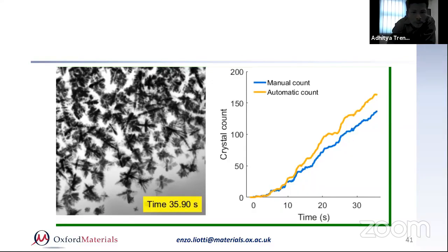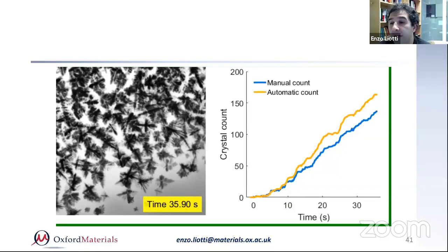Maybe the type of flow is laminar flow, if I'm not wrong. It is laminar, quite likely, yes. You would see what happens in the mushy zone. You're not going to replicate what happens in the flow when you cast, for example, in the filling system, right? But you could replicate what happens, for example, in a filter. I haven't shown it, but we did some experiments in which you can see the liquid. If you add a little bit of lead to your aluminum alloy, the lead will form a monotectic reaction.